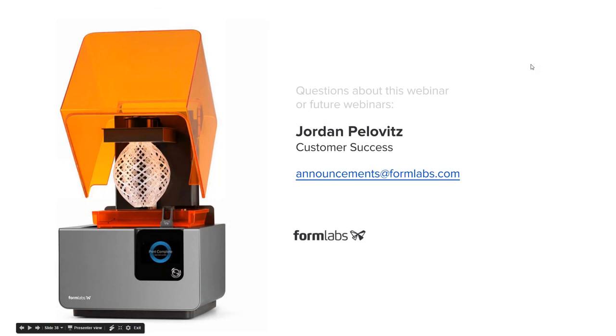I've been using a 40-watt black light for post-curing. It definitely works, but I have no idea how well. It usually takes a couple of hours before the resin is drying hard. Any comments? Add some heat and make sure your black light is using that 405 nanometer wavelength if possible. That'll definitely increase your effectiveness. And one addendum to that is to make sure it's at like 60 degrees Celsius.